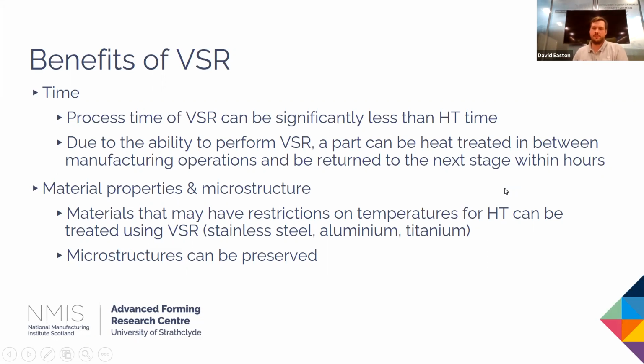Again, on material properties and the microstructure, you can have a number of materials that you're restricted with for high temperature, especially things like stainless steel or aluminium or some titaniums. There is a real restriction on how high you can go temperature-wise to stress relief before you start to reduce strength or reduce hardness in particular. So by using VSR instead of the thermal process, you can preserve those microstructures or those material properties.